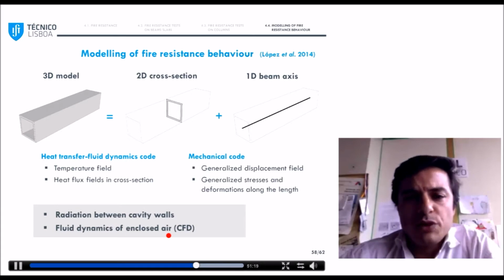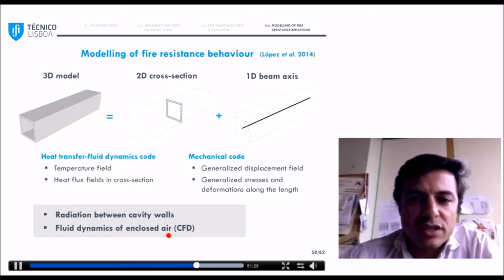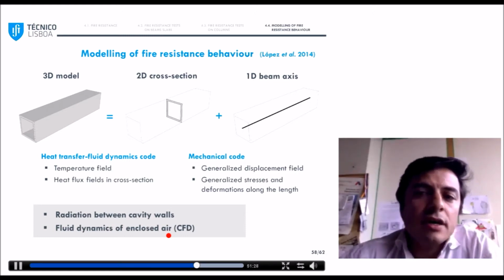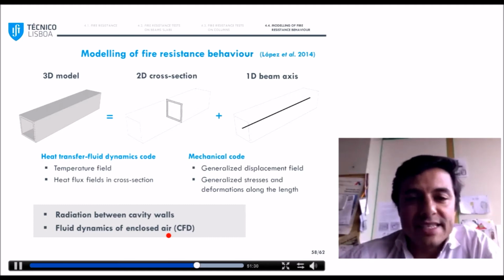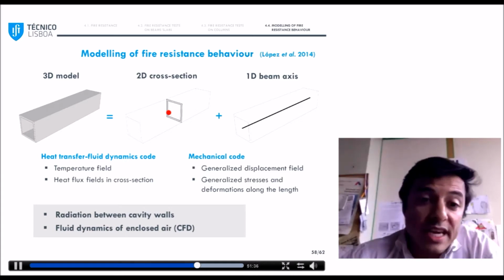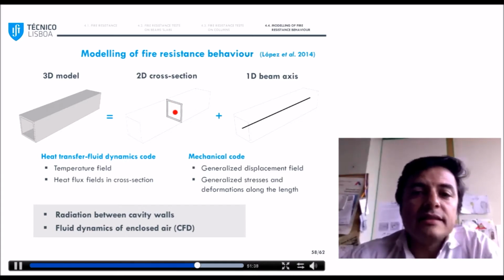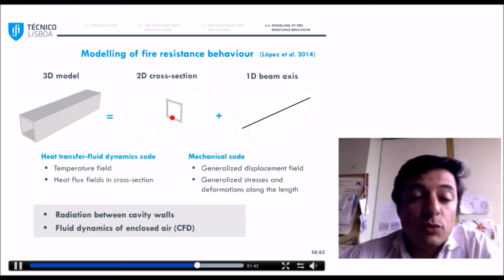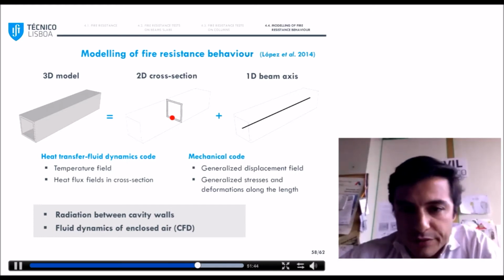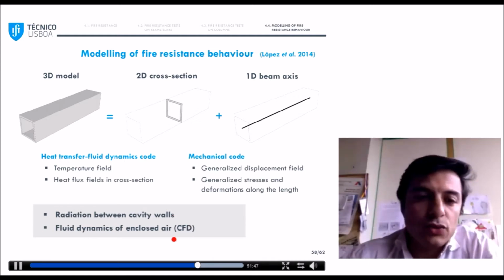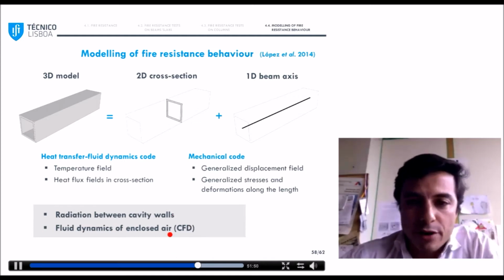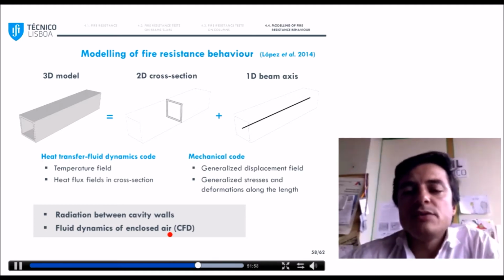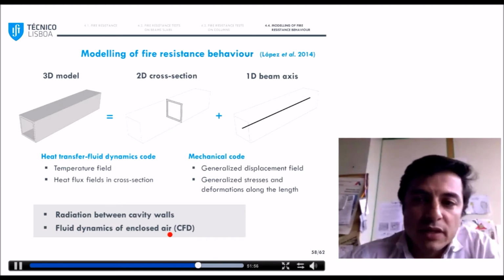First, we did 2D numerical simulation of the thermal response of the section, and the main innovation here was the consideration of the heat exchanges in the cavities of the walls due to the radiation between the walls and the flow of the air enclosed in the cavity, which for some cases proved to be quite relevant. For this, we had to use a CFD code with our thermal model. Then, as for other studies, we use these thermal responses as input in a geometrically nonlinear beam model.